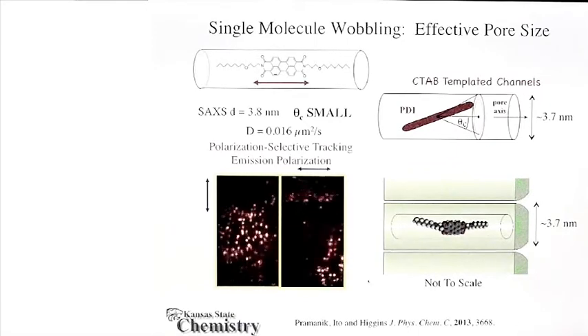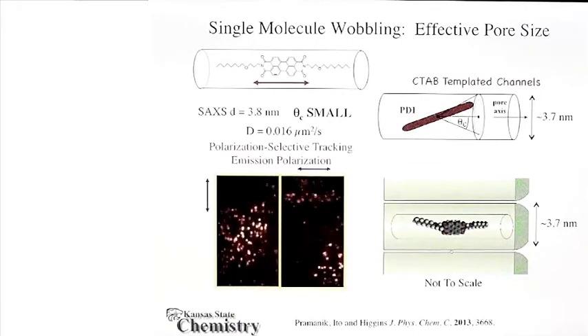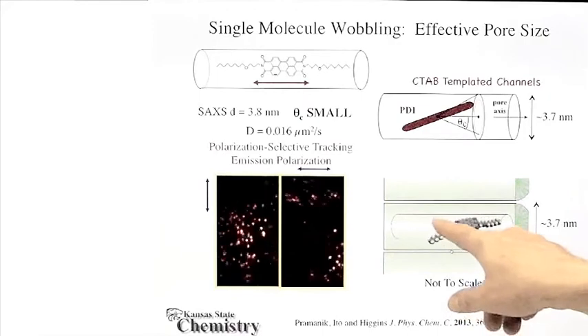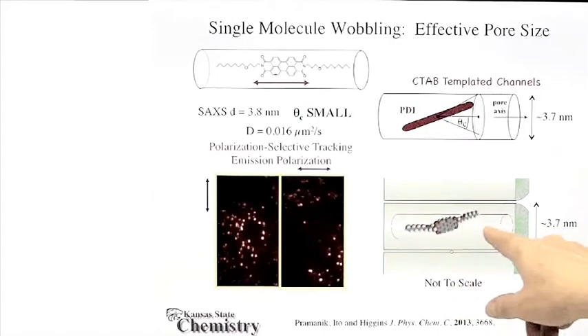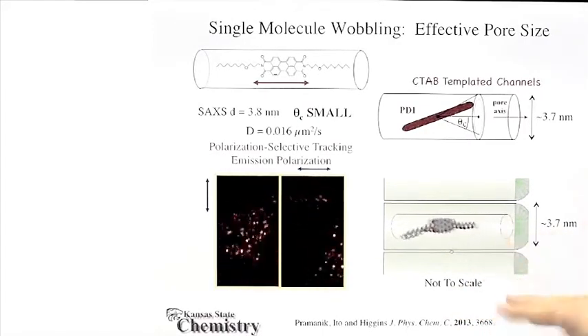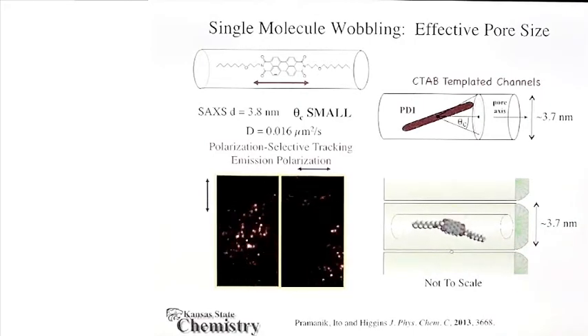We view these motions as a wobbling of the molecules about their long axis within the cylindrical mesopores, as shown in this cartoon video on the right, where we see the molecules wandering up and down the long axis of the nanochannels by Brownian-like motion as they wobble and tilt within the channels.